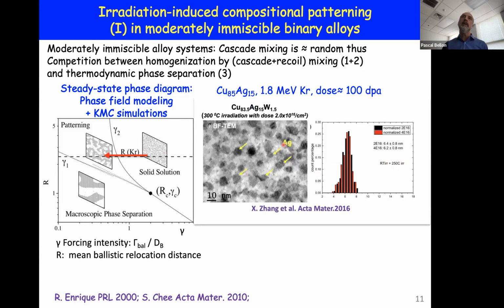And here's an illustration on a very similar alloy, where in bright field mode, the silver-rich precipitates are identified through their moire pattern, those fringes here. And on the right-hand side, you have size histograms for those precipitates from a dose and a dose twice as large. And you can see that the size histogram hasn't changed at all, confirming the steady state nature of these nanoprecipitates.